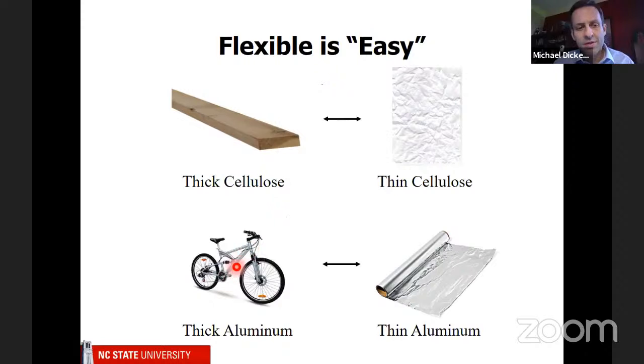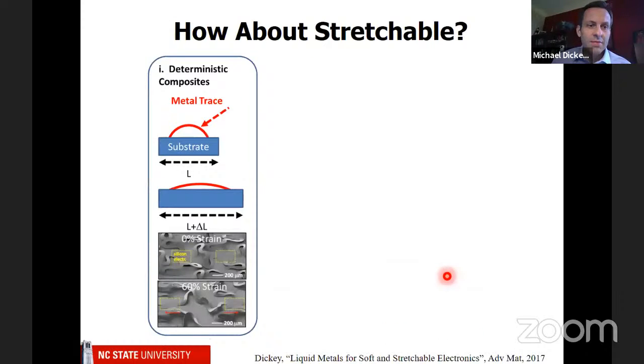Same thing for aluminum. This is a bicycle made out of aluminum, and if you make it thin enough, then you have aluminum foil. But neither one of these is stretchable and neither one of these is soft. So one way to make them stretchable is by taking these same materials. Imagine you have a piece of metal that's very thin and you can bend it. I can make it sort of stretchable just by bending it in and out of plane. So this is one approach that people have taken.